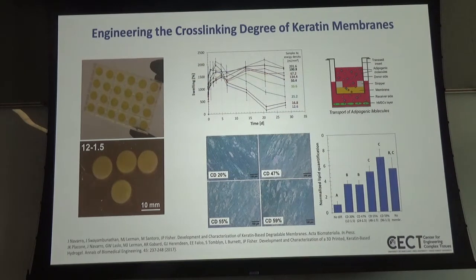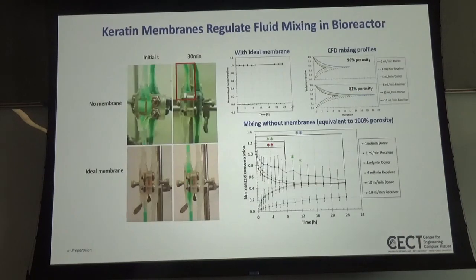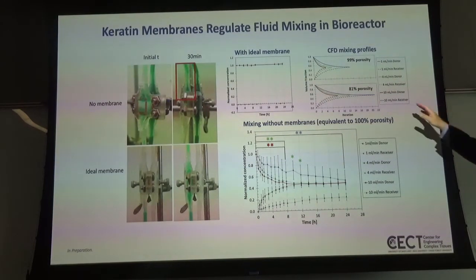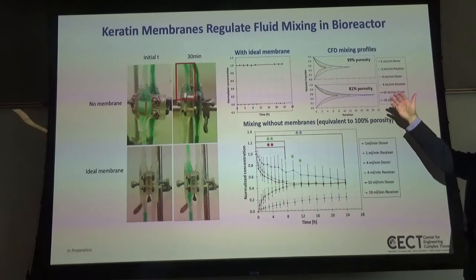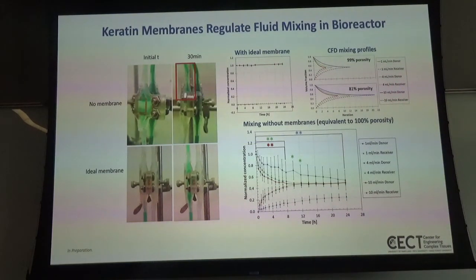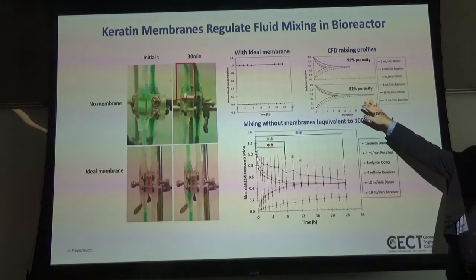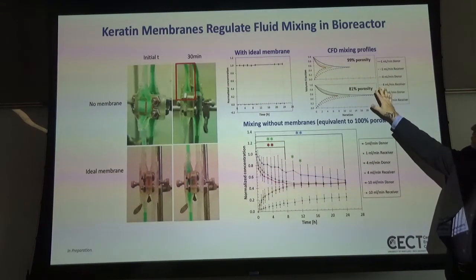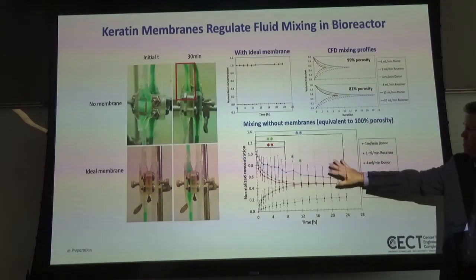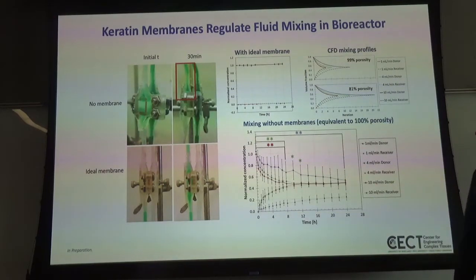So then, going back, he took these membranes that he's printed and created, put them back into the bioreactor system, asked similar questions about fluid mixing as a function of the porosity of the membranes, and essentially, if you have a very, very tight membrane, you're not going to get a lot of mixing between the two chambers of the bioreactor, but as the porosity increases, we get more and more mixing. And you see this was computationally done, and this is the experimental result that kind of validates that approach.